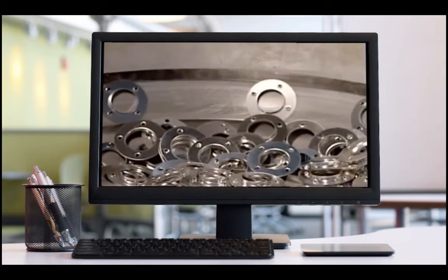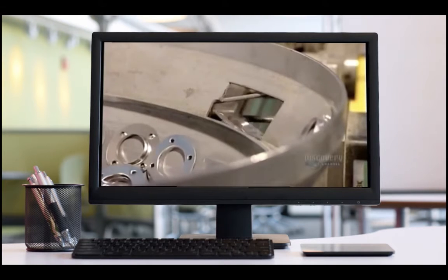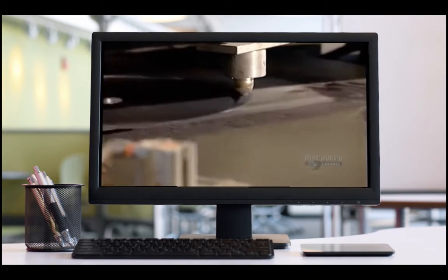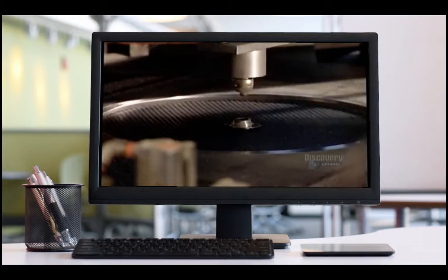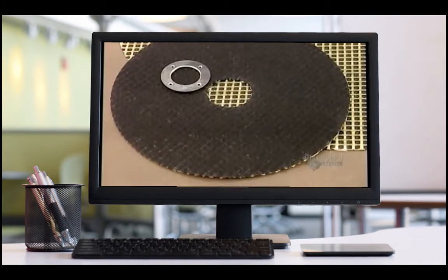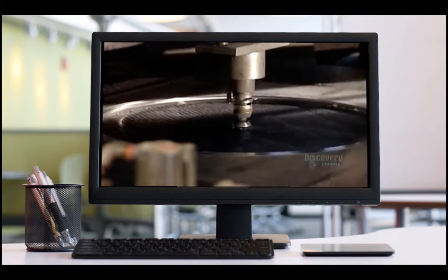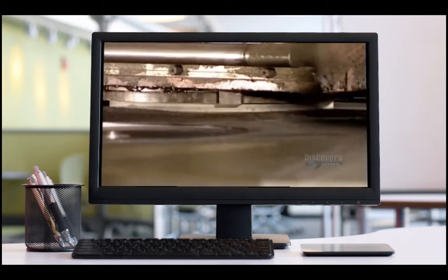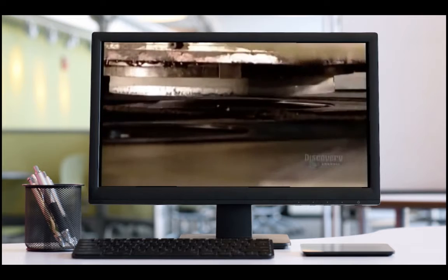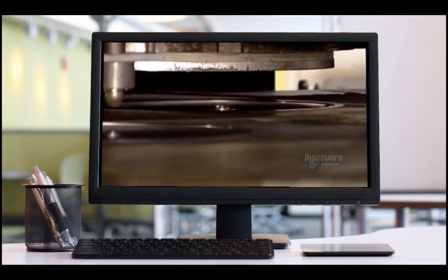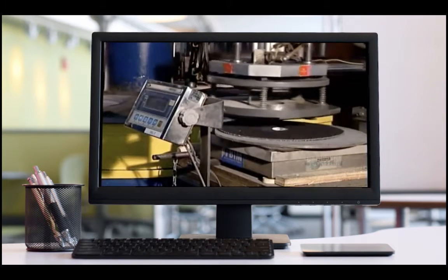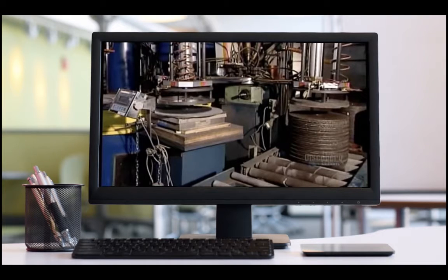A galvanized steel ring is placed in the center of each wheel, with four small anchors gripping the mixture; this ring is designed to protect the shaft that spins the grinding wheel. A hydraulic press then compacts the material, applying up to 350 kilograms of pressure per square centimeter — the equivalent weight of about 30 cars. Every single grinding wheel coming off the line is weighed to ensure it meets design specifications.